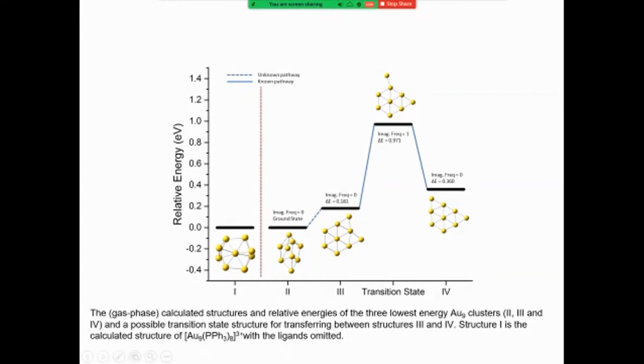That means when we deposit this gold nanocluster, it changes in terms of the deposition. There is one structure, the isomer here, that we couldn't find, because this is actually a transition state, and it's hard to visualize by the STEM. As far as you know, this is the smallest gold nanocluster that has been seen in the literature.